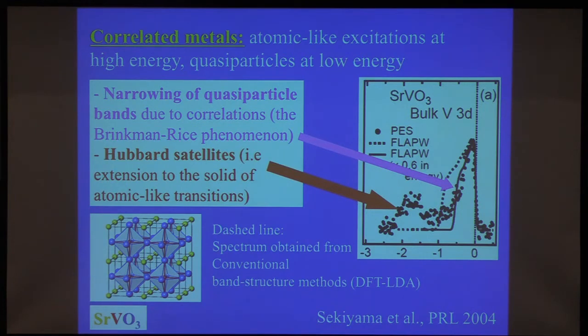However, if you do a band structure calculation, which is based on the DFT formalism, an exact formalism, plus approximations, unfortunately, that we have to make to the functional of the total electron density, so this is the state of the art for electronic structure calculations, what you find is that this excitation spectrum is lacking all these atomic transitions. And this is because you forgot the atoms. So what was very easy to explain to a 5-year-old child in terms of atomic transition is now lost because you've decided to focus only on the electrons. And furthermore, as you see here, the bandwidth, or the kinetic energy available to this delocalized electron, is too large by a factor of 2 in this case.